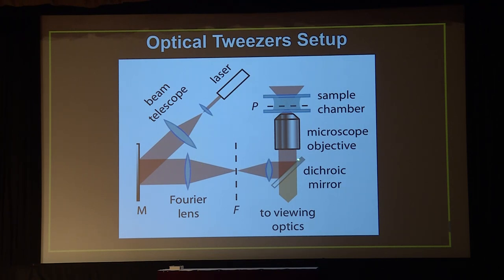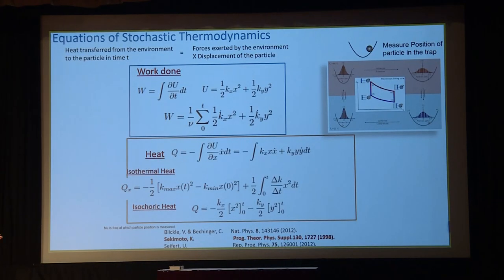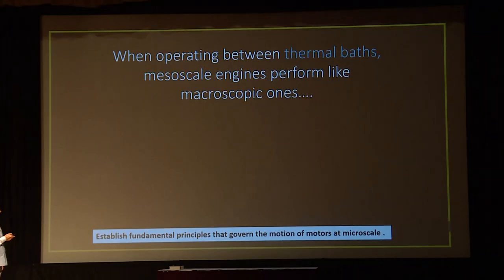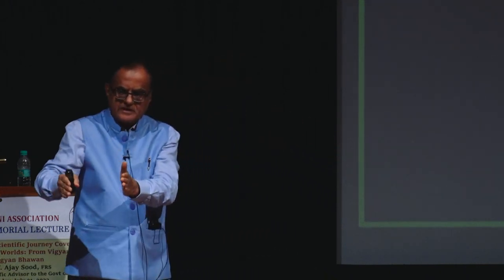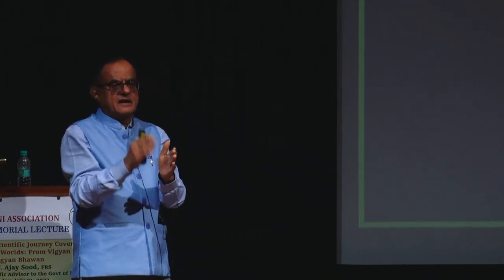You focus the laser in a microscope, and this is where you trap a colloidal particle, and you can move it around like a tweezer. I will not go over the equations, but once you know the probability distribution, you can really get all the heat and work done. And what was found in 2012 is that when you operate between thermal baths at 70 or 80 degrees centigrade and room temperature, whatever you measure, the work done, efficiency and power, exactly match what you calculate for macroscopic engines. So the microscopic engine gives you the macroscopic result when you work with thermal reservoirs.